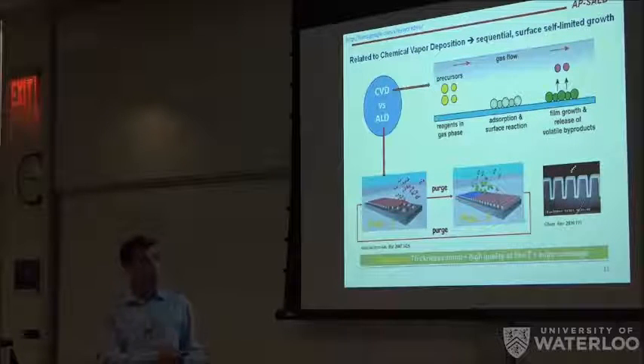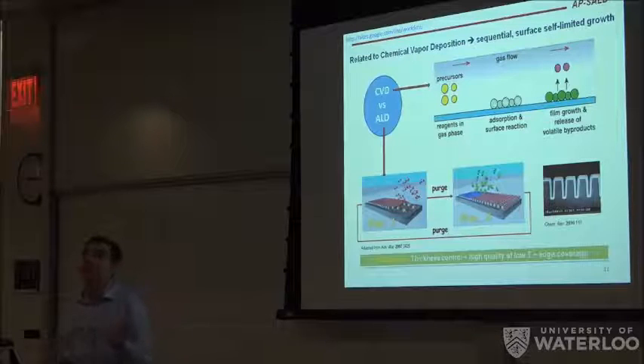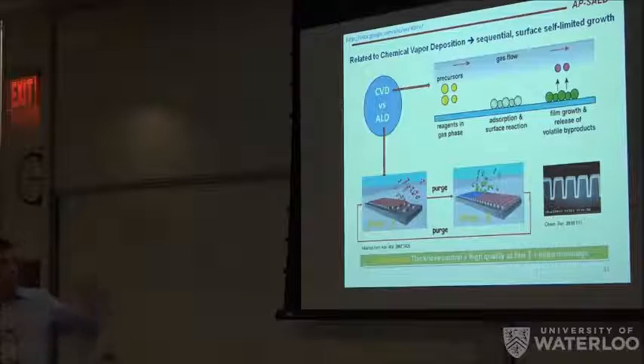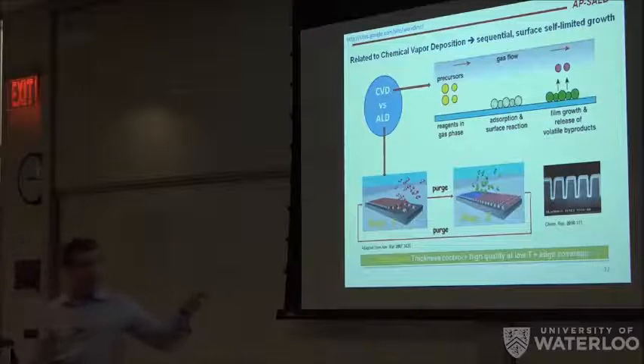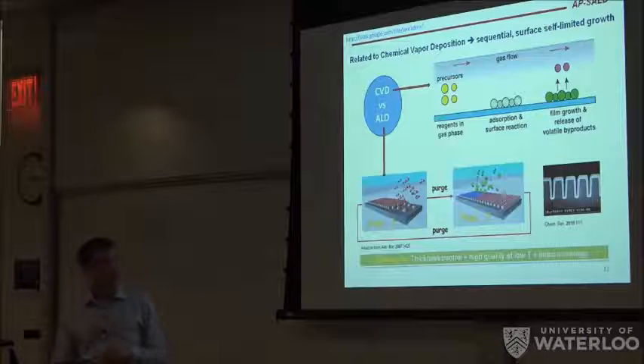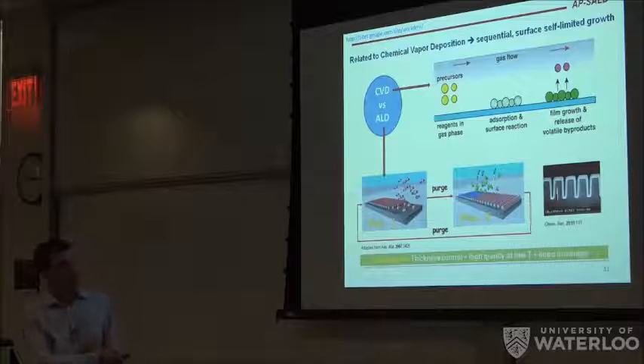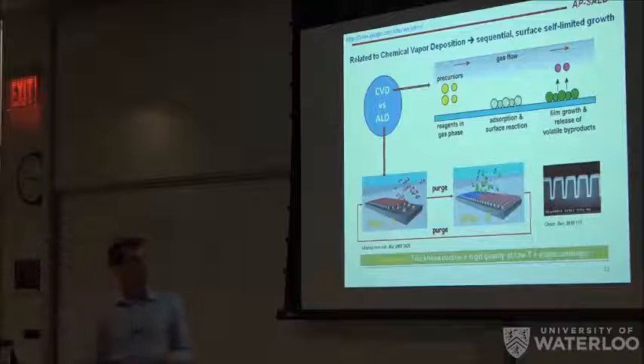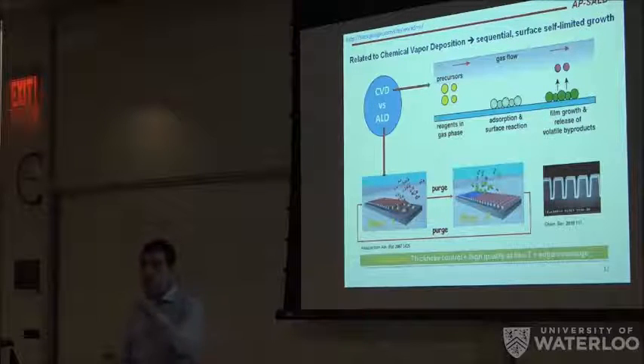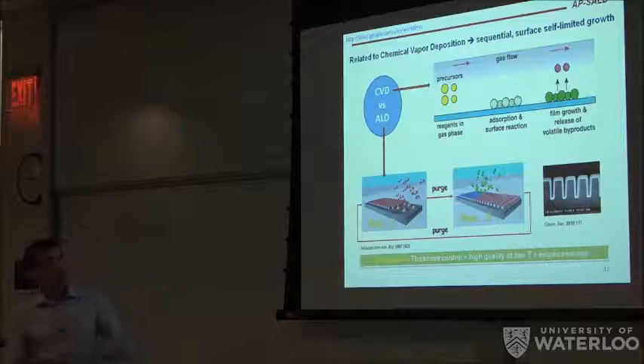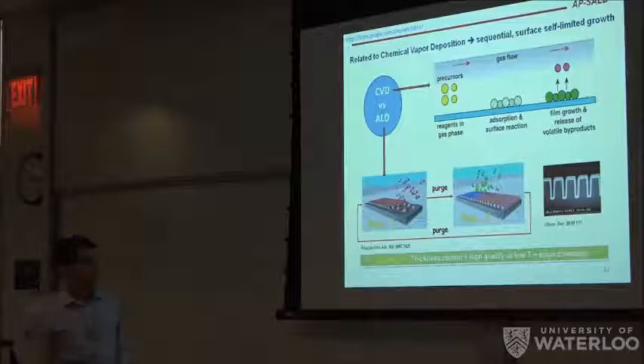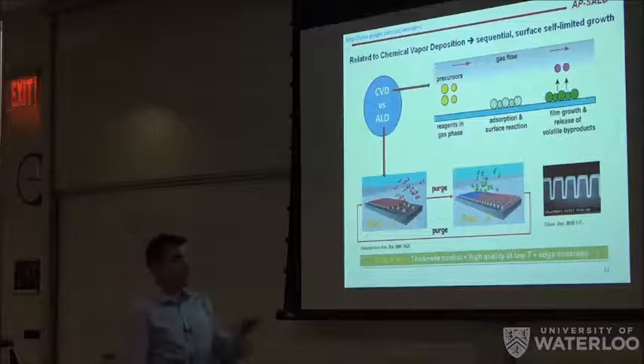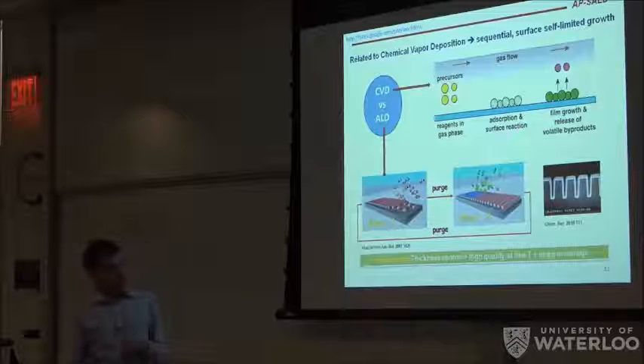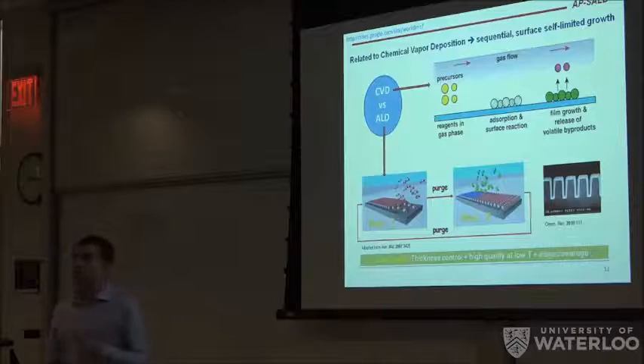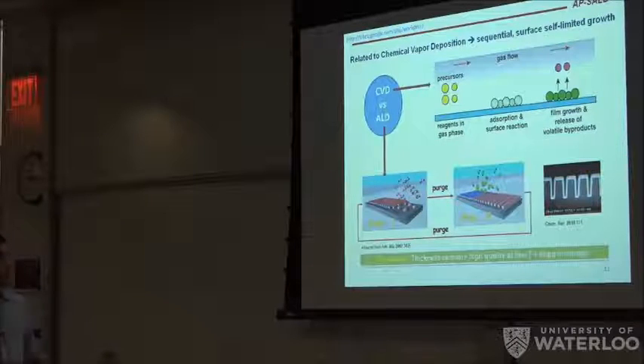The other unique property is that it's the only technique that allows a uniform and nice quality film over high aspect ratio features, because the precursors have enough time to diffuse and to react with all the surface. And then you can see that the film is homogeneous, the thickness is constant, and the same is valid for large area surfaces. It's the only technique that can give you a very homogeneous film. And the third quality is that the films that you obtain are quite high quality, even at low temperatures.